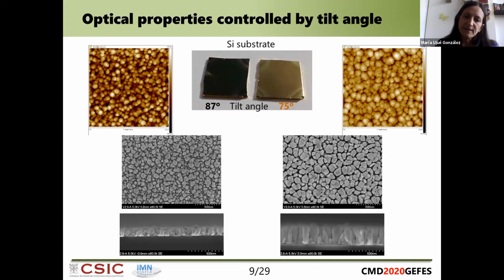So at 75 degrees, for example, we got a gold layer, a little bit dark, of course, because it's not flat, it's full of columns, it's very nanostructured. But at 87 degrees, what we were getting was a very dark, almost black film. Okay, and the morphology of the two different films is slightly different. Here we can see that we have smaller nanocolumns, and in the other case we have bigger ones.